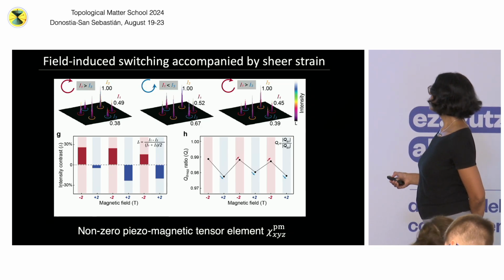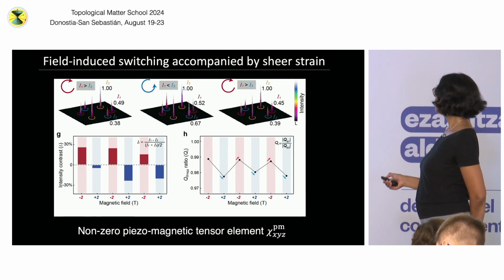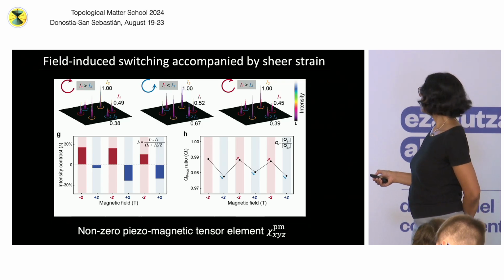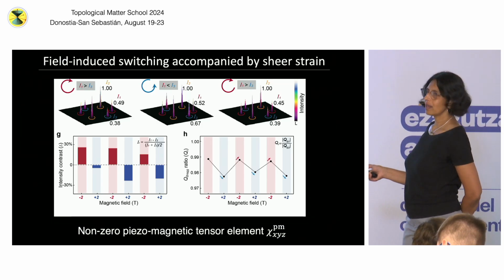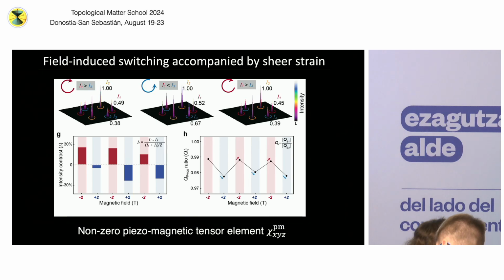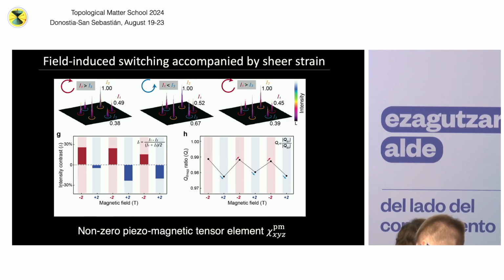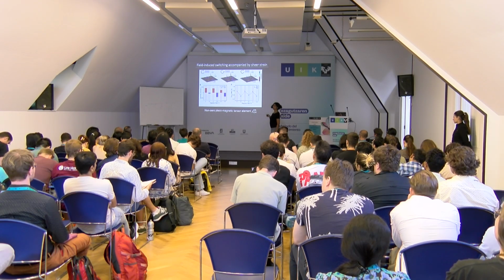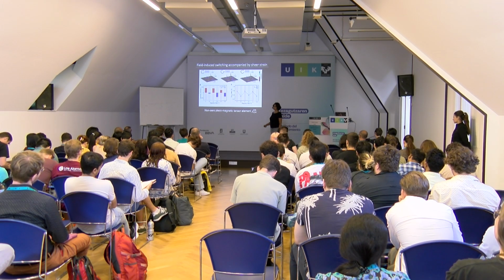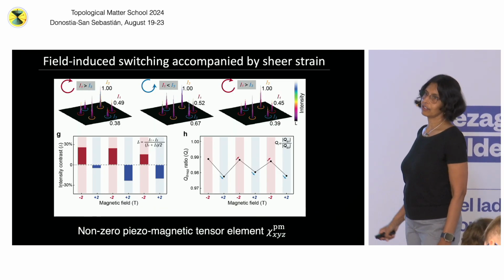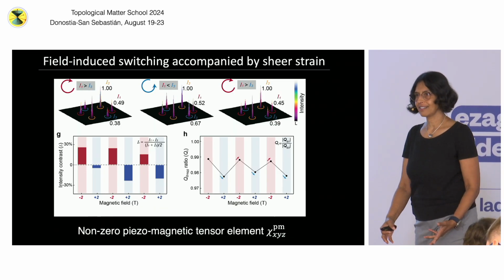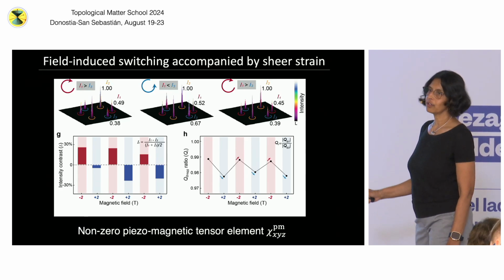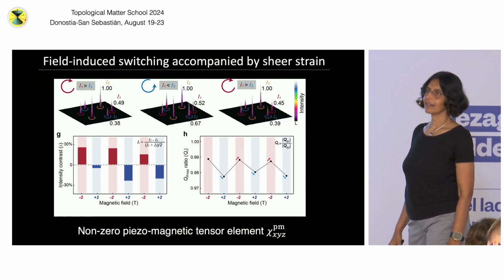The amplitudes never match. But I'll tell you the reason why this is so important. STM people usually don't take these intensities seriously unless you can manipulate them, because there's always some tip effect. Let's say you turn on the field and something changes. How do you know your tip hasn't changed? That is why this is so important. This gives credence to this. The Bragg peak distortion, that is real. That is not a tip effect. So when this and this go hand in hand, you know something real is happening. Okay, I see.